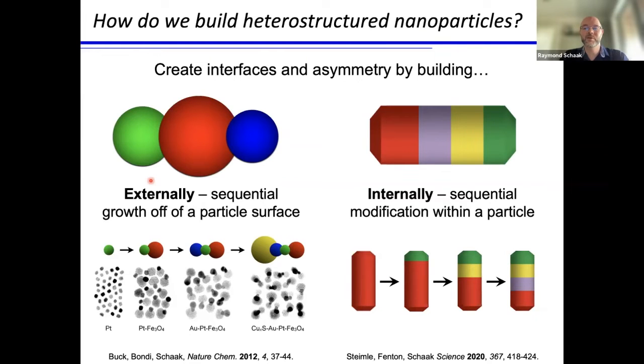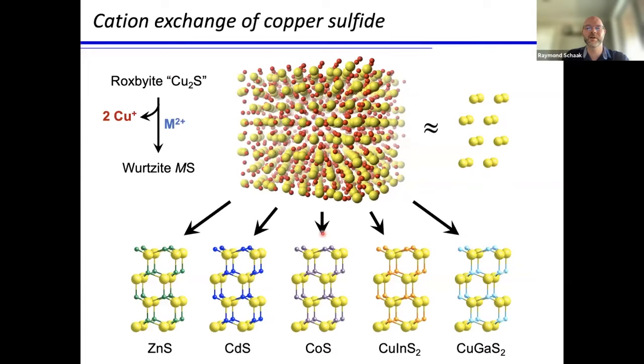The other approach, which is what I'll focus on today, which is in line with the transformative inorganic nanoparticles theme, is internal modification of a seed nanoparticle. So instead of growing externally, we're creating interfaces and modifying composition within the nanoparticle. For example, through sequential, in this case, cation exchange reactions that transform a simple starting material into a nanoparticle that's much more complex compositionally, in asymmetry, interfaces, functionality, et cetera.